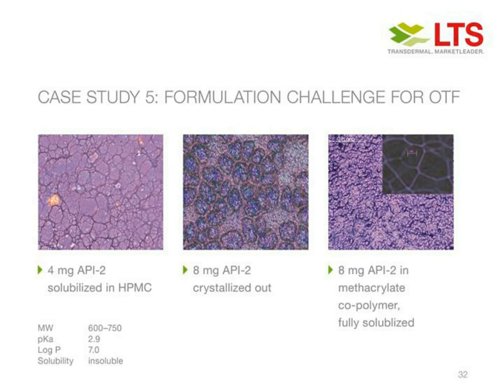What we have done with this particular API was to change the polymer platform. On the right-hand side, instead of using HPMC, we use the methacrylate copolymer. You see in the inset, essentially the drugs are all dissolved in the polymer matrix, and this is a very important aspect when we come to the formulation of oral thin films. How do you strike the balance of maintaining the product in solution or in crystal form without recrystallization, and also the growth of crystals from your suspended particles?